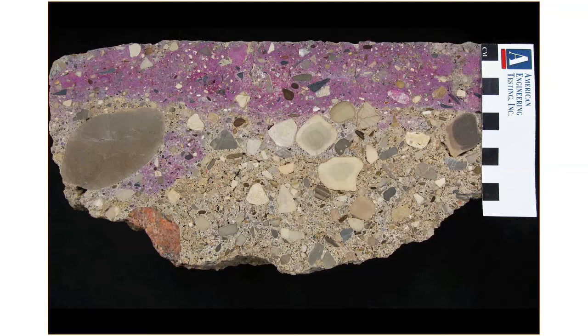And what this is telling us is that this cap, the second lift of concrete mortar on this pavement, is extremely dense and extremely impervious, and it has resisted this carbonation, this chemical change that occurs naturally in concrete, for 125 years. This is special. This is very special. So the open nature of the under consolidated, almost honeycombed lower lift is fully carbonated. And so that's what we're seeing there. So very interesting as we talk about the quality of this concrete and how it's been able to survive for so long.